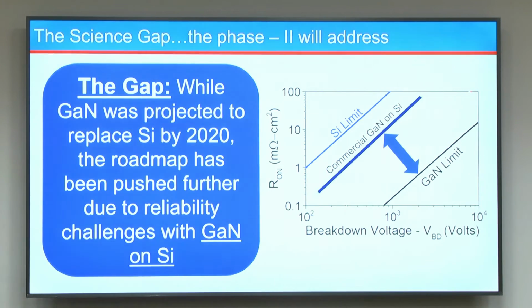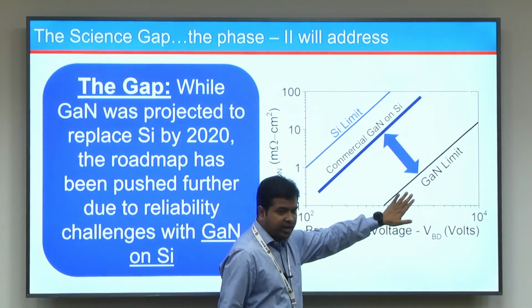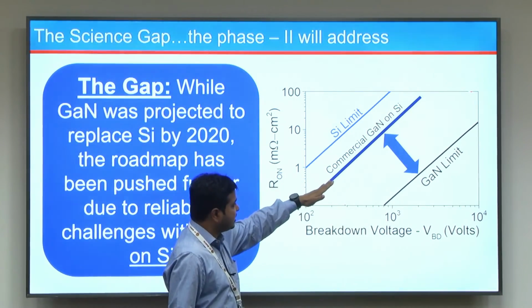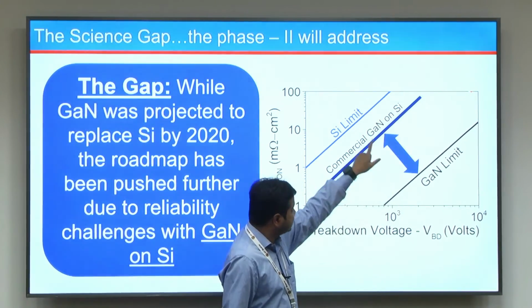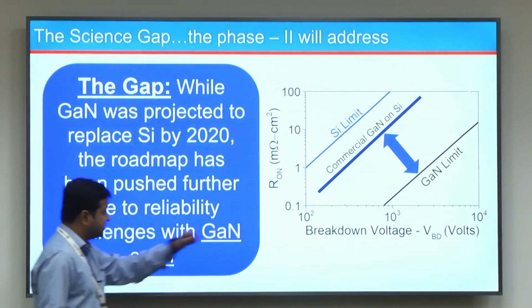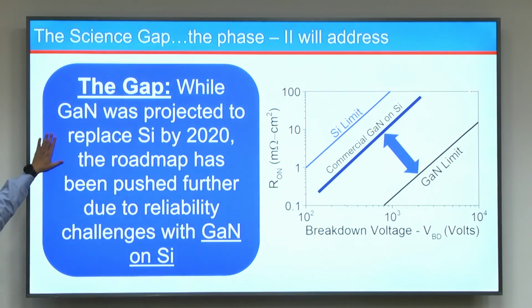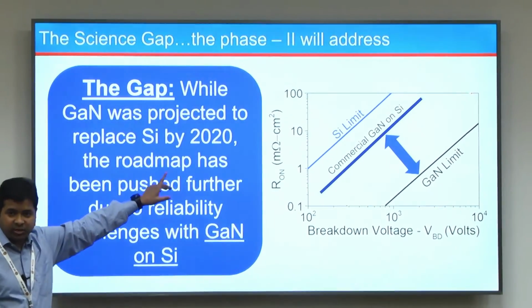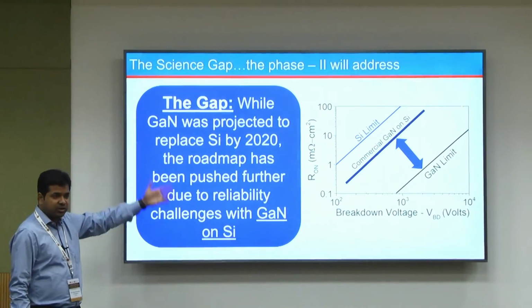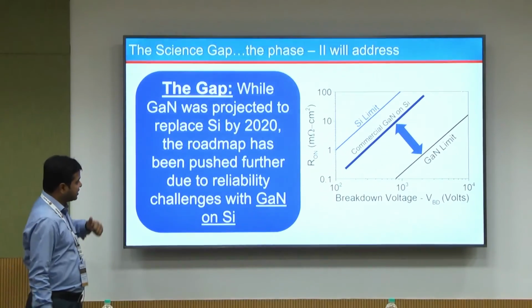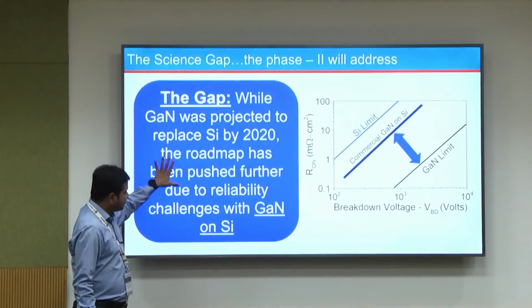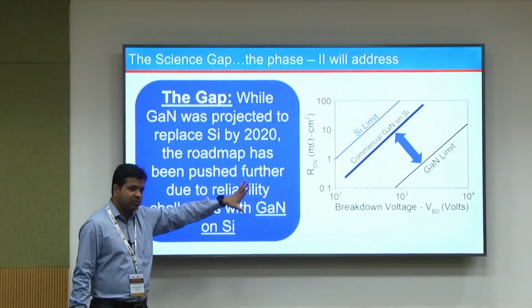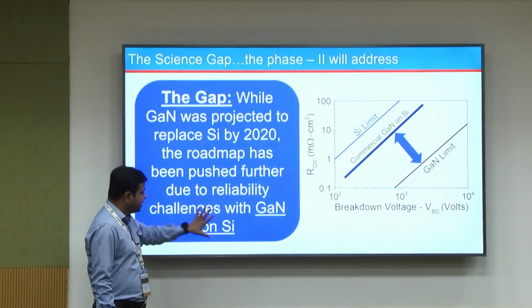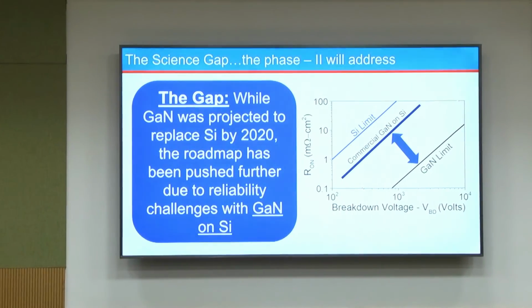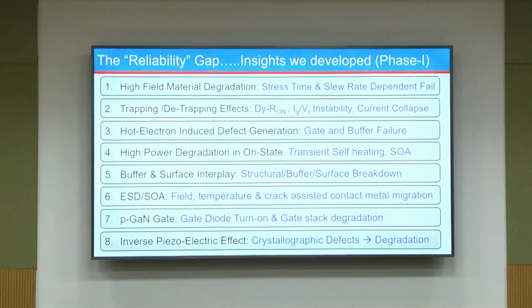So if you see, as I told you in the beginning, this is the GaN theoretical limit, but the commercial devices are somewhere here. There is a big gap here, right, and this big gap is attributed to reliability, which is why, while it was projected back in 2014 that GaN will replace silicon by 2020, it has not yet replaced silicon because of a lot of apprehensions from the customers and from the system manufacturers. And this push has been held back because of this big reliability gap, and if we address this reliability gap, we can basically get GaN devices to market, and that's what we are trying to address.